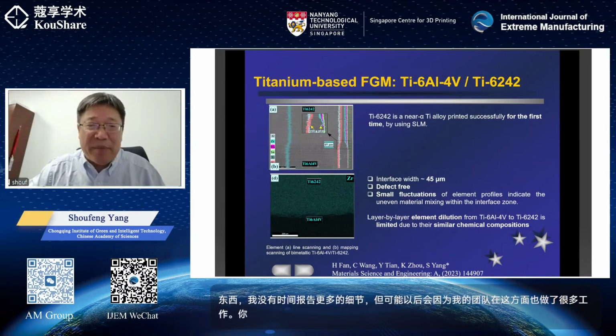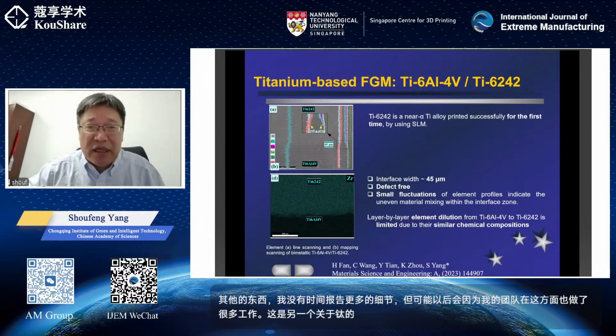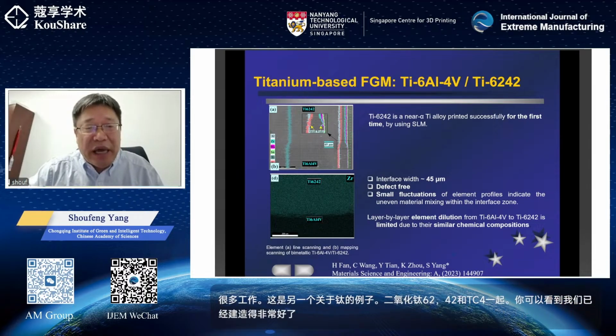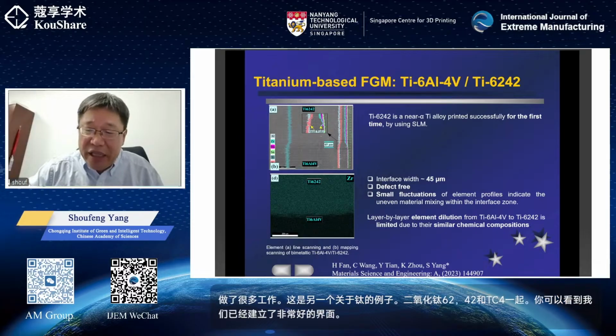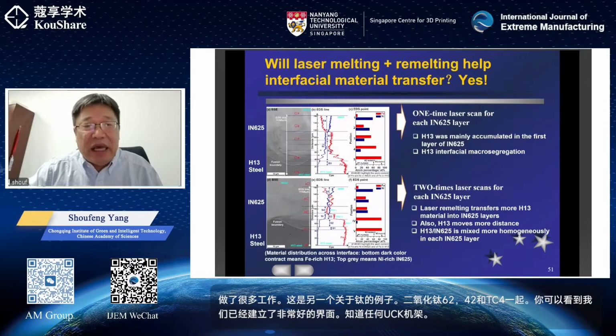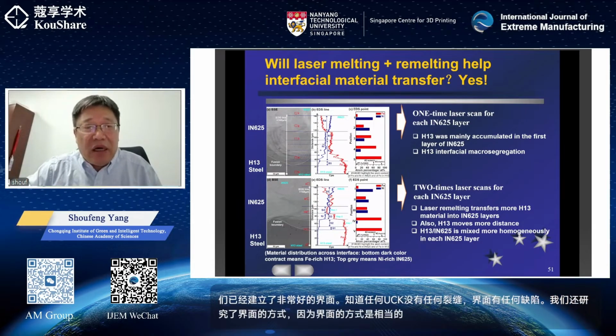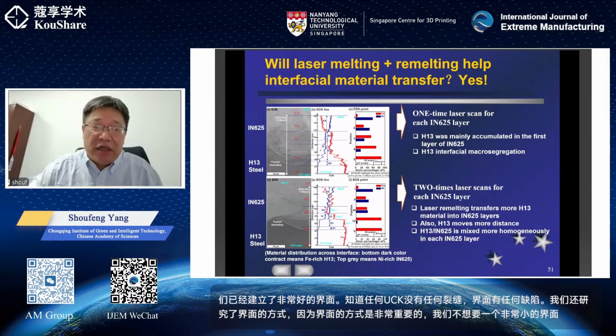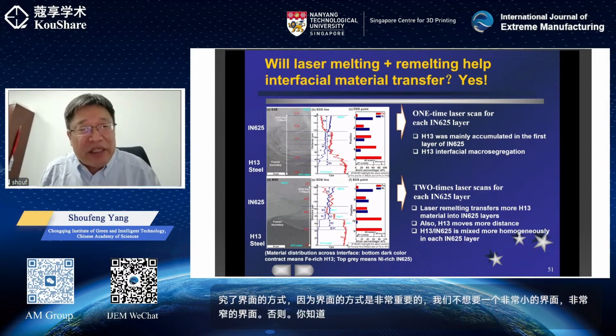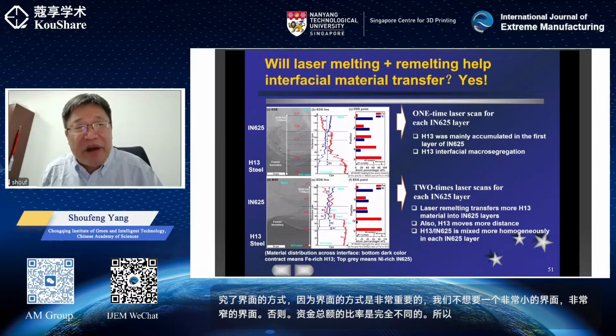Here is another example about titanium. Titanium 6242 and TC4 together. And you can see we have built a very nice interface, without any cracks or defects in the interface. And we also investigate the width of the interface, because the width of the interface is quite important. We don't want a very small, very narrow interface. Otherwise, the thermal expansion rate is quite different, so you can have a very big thermal stress.